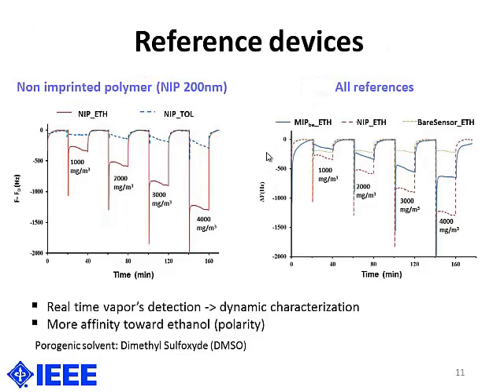This figure represents the real-time detection of vapors, so ethanol in red and toluene in blue. So adsorption and desorption. This shows the possibility to characterize dynamically the thin film layer, and we can also show a much better sensitivity towards ethanol, so the polar molecule, compared to the toluene.